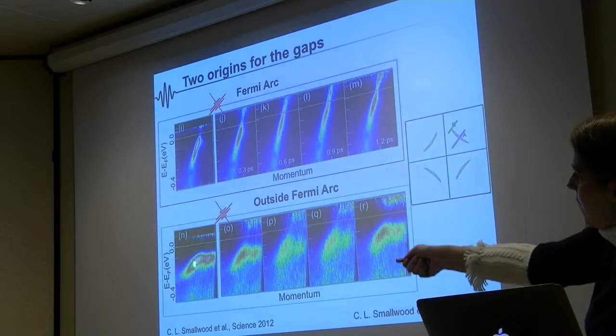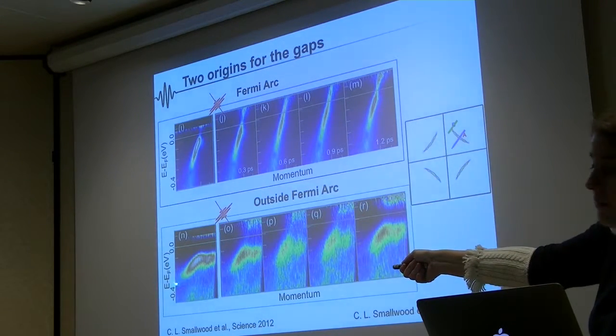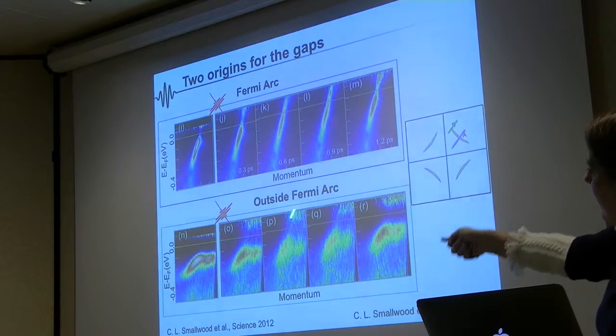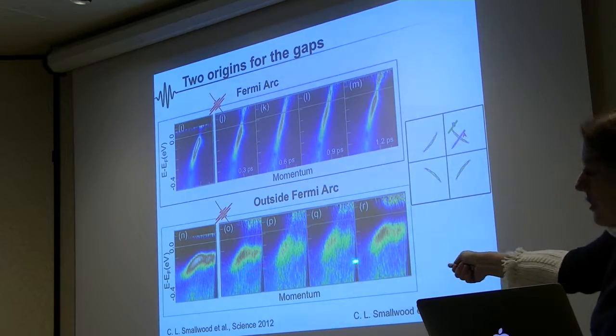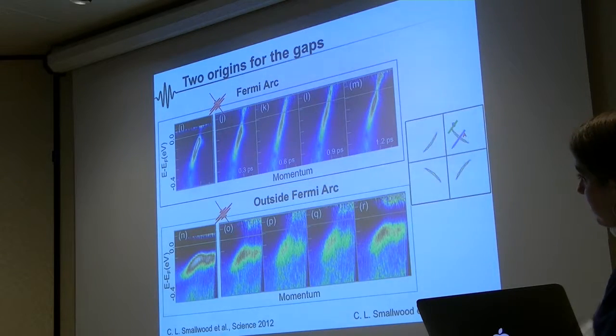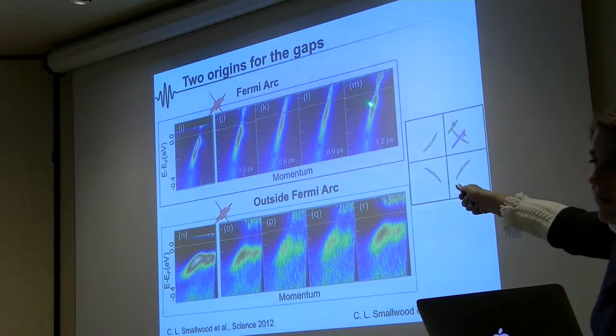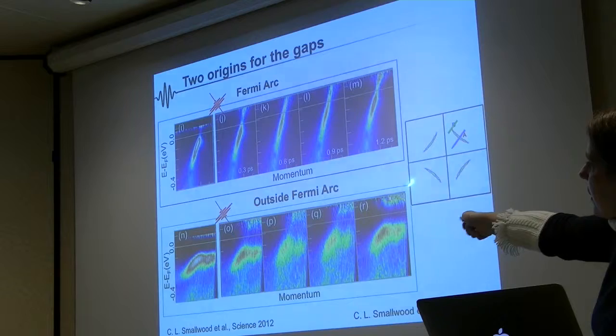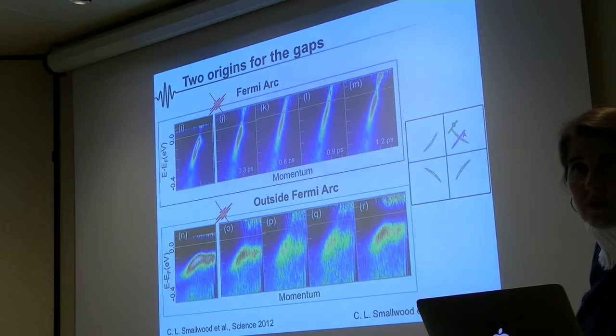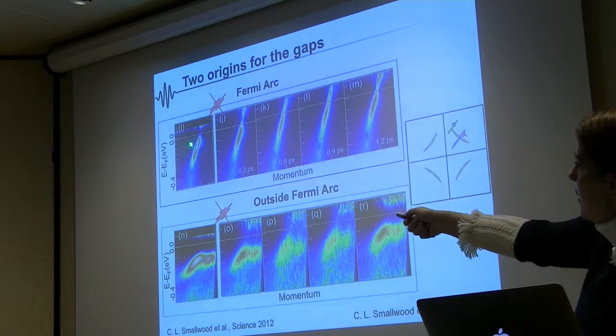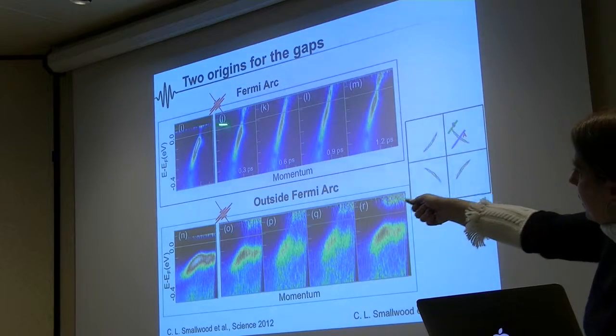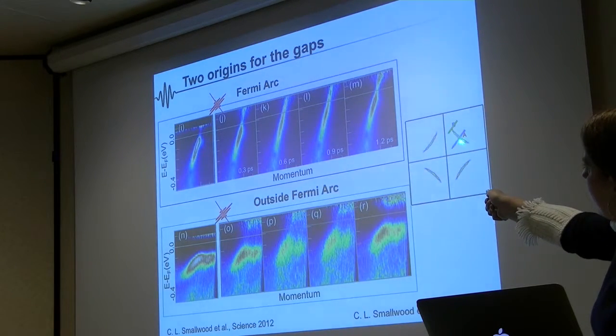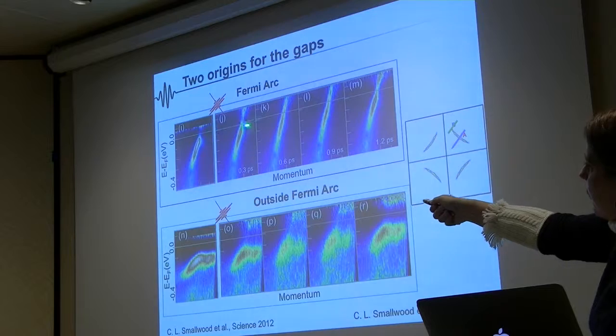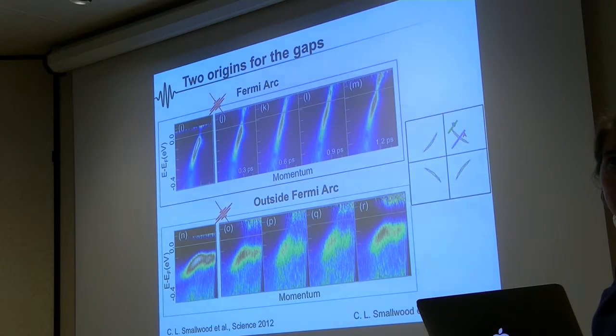So these are equilibrium spectra. Everything is divided by the Fermi function. And these spectra here are all transient spectra, so non-equilibrium spectra. So you clearly see a very big difference here. Here I'm using the maximum fluence that we use, so this is 10 microjoule. And you can see that when you are sitting at any point on the Fermi arc, at those high fluences, you completely close the superconducting gap.